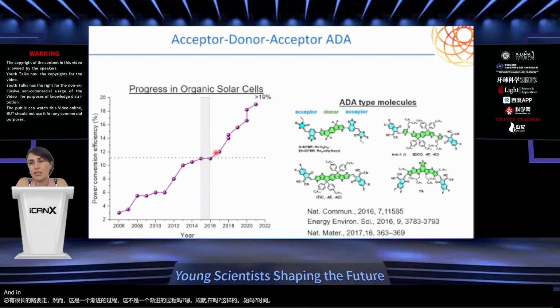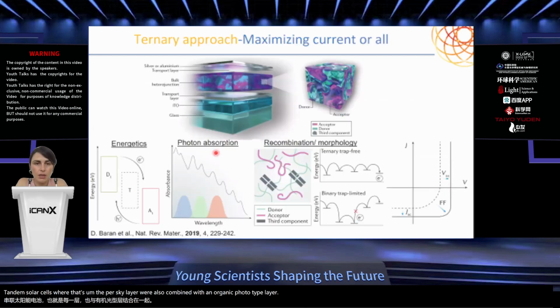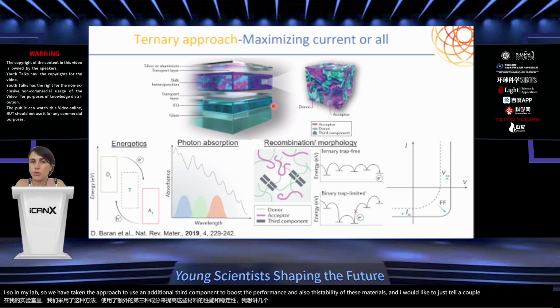In fact, these materials not only impacted organic photovoltaics, but also the perovskite field, where you might find tandem solar cells in which a perovskite layer is combined with an organic photovoltaic layer. So in my labs, we have taken the approach to use an additional third component to boost the performance and also the stability of these materials. And I would like to just tell you a couple of stories.